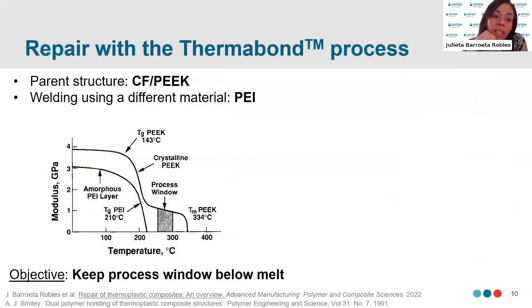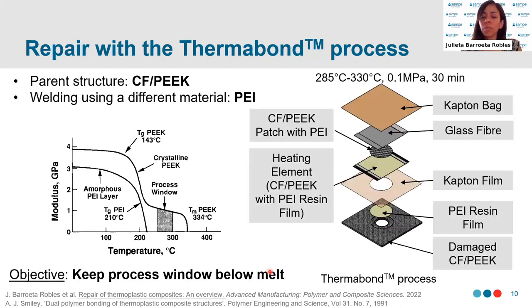So in the Thermabond process, the parent structure was made out of carbon fiber PEEK, and the patch was joined using polyether imide, so PEI, as this material is amorphous and compatible with PEEK. Now, this material can be processed at lower temperatures, and the objective was to keep the process window below melt. This would allow them to prevent melting of the parent structure and inducing further damage or other defects such as delaminations. So in this demonstration, we saw a carbon fiber PEEK damaged structure being repaired using resistance welding, which meant there was the need for a heating element.